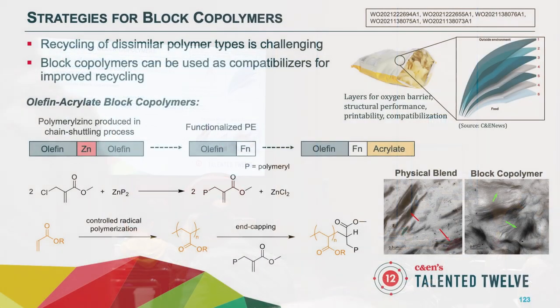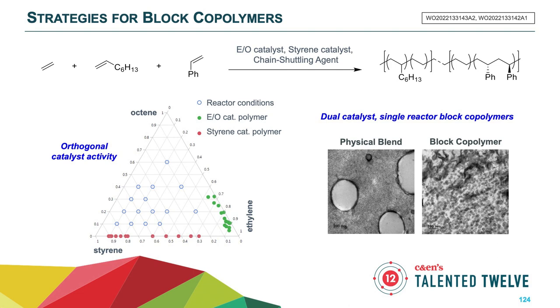And you can characterize and confirm that you've successfully made this polymer through a number of techniques like diffusion NMR and GPC, for example. And you can also see it visually. Under the transmission electron microscope, you can see that in the case of the physical blend, all the crystals are really tightly packed together. Whereas when you successfully form a block copolymer, you get exfoliation of the polyethylene crystals, suggesting that you've compatibilized these polar and nonpolar components.